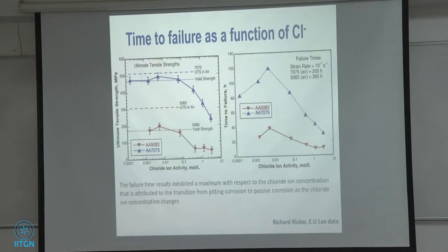So there is a competition between passivating layer and dissolution of the passivating layer. It's kind of down. But who wins in the end? The dissolution. Okay? Because once the dissolution of the passivating layer took place, then it's going to start corroding more. So the trends are the same, both for the 5000 and the 7000 series.